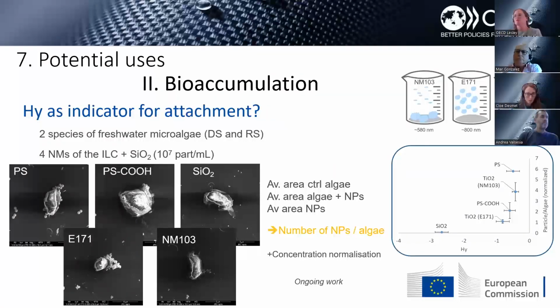We also started to study the potential effect of hydrophobicity on bioaccumulation by performing contact tests with the nanomaterial on two different species of freshwater microalgae. We measured the average number of particles binding to the algae, to assess a possible correlation between the hydrophobicity index and the attachment on the algae surface.